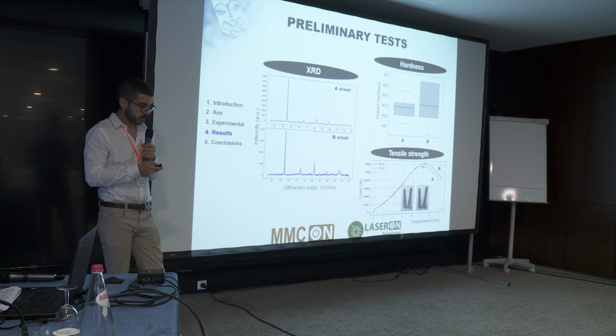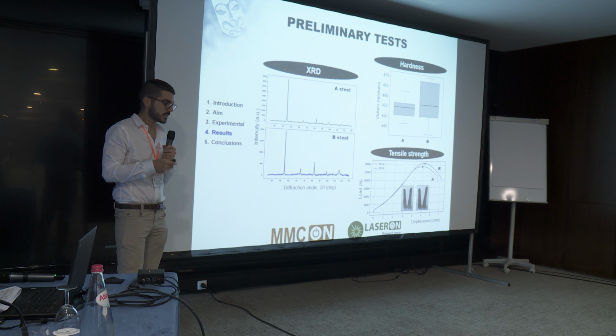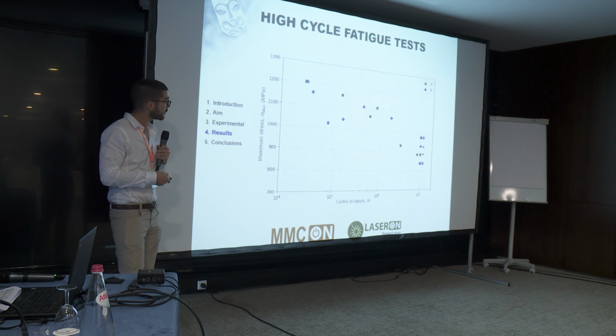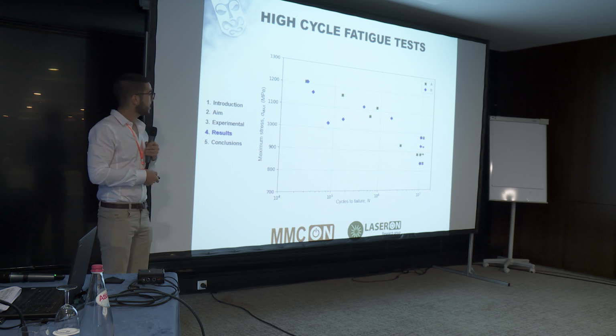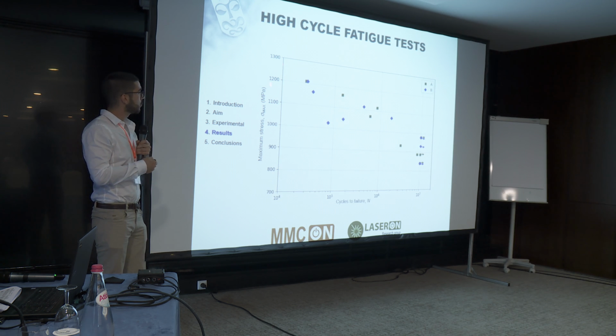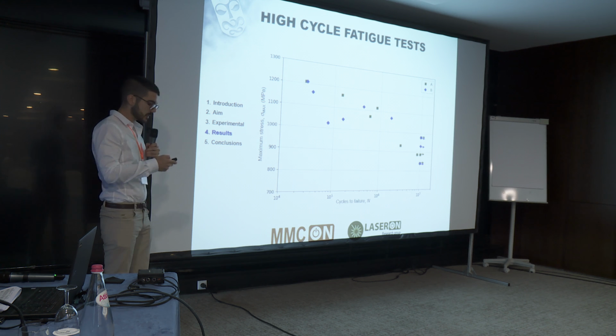And we also performed tensile tests on a few specimens, and here we did see that B steel presents a not much higher, but I think it was a 7% higher tensile strength than A steel. So here I'm presenting the fatigue results under normal test conditions, let's say.